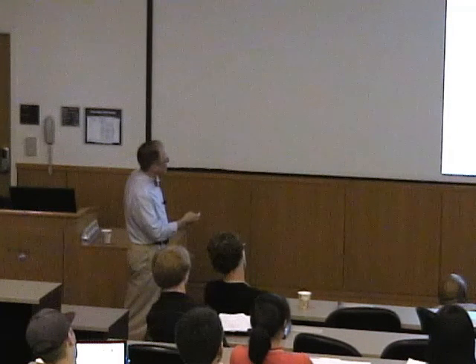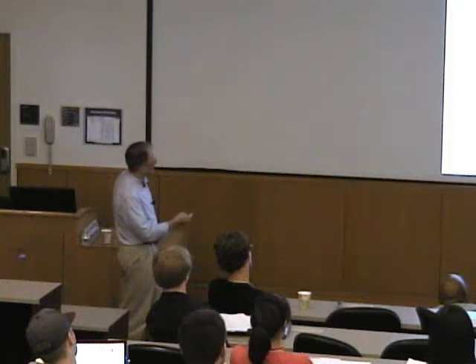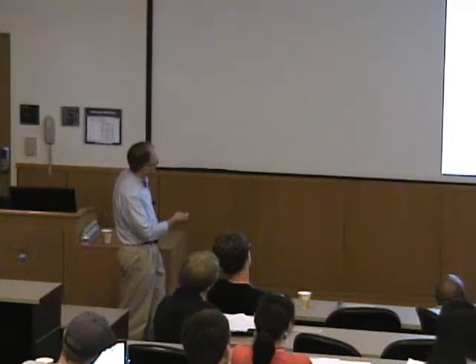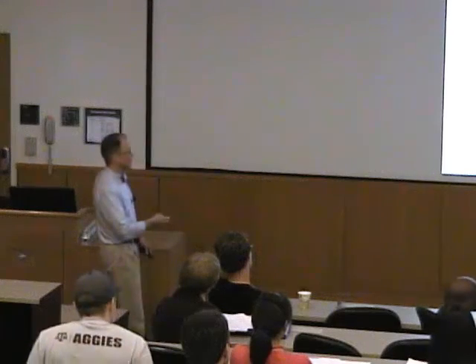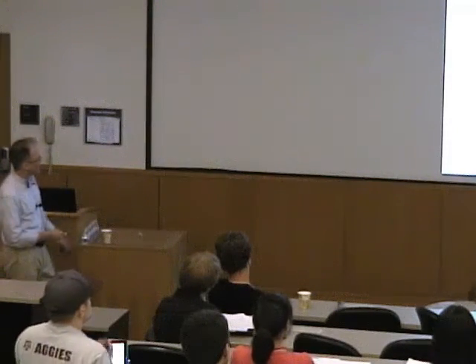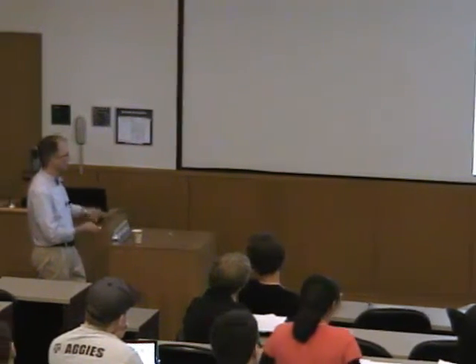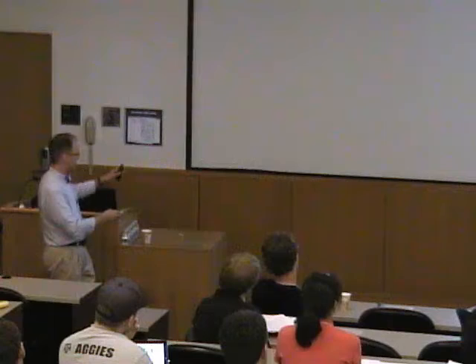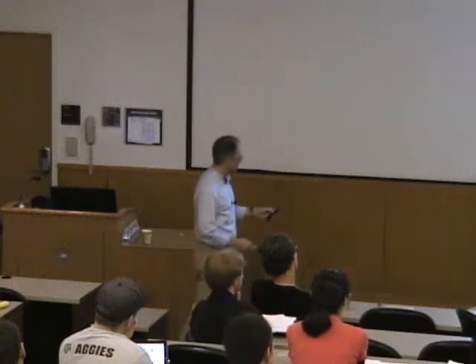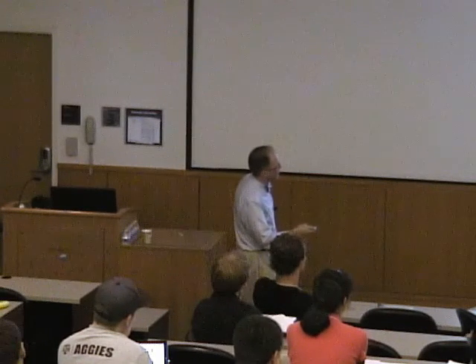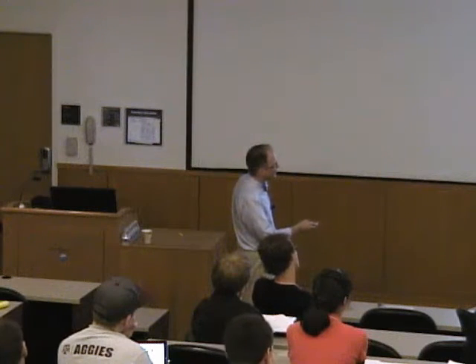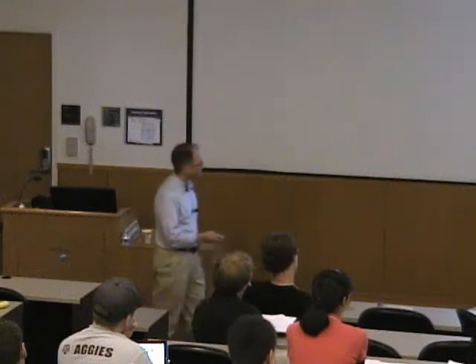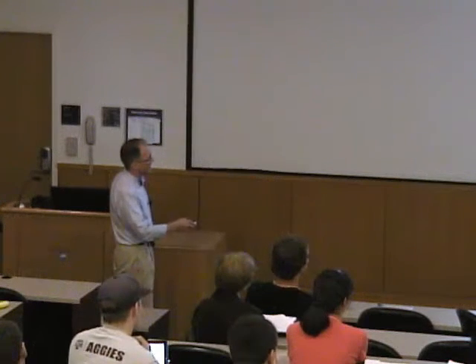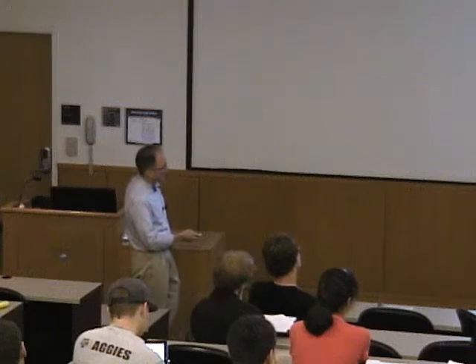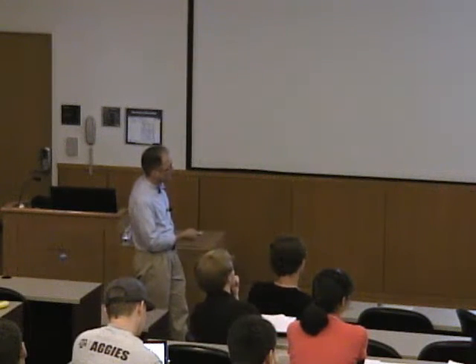But as soon as we would increase the scan rate, everything would go to not a nice place. The data starts to look very asymmetrical. Graciously, we could say it looks quasi-reversible, but then quite irreversible the faster that we go, and this behavior was completely reversible. That is to say, we could start slow, speed things up without moving anything, dial the scan rate back down, and we have that nice reversible behavior again. So what that told us is that the rate associated with electron transfer, and this is where we can tell something that's slow from something that's modestly fast, in that mercaptoundecanoic acid case is a relatively slow rate. It's also about the rate associated with the actual HAO turnover with cytochrome C554.